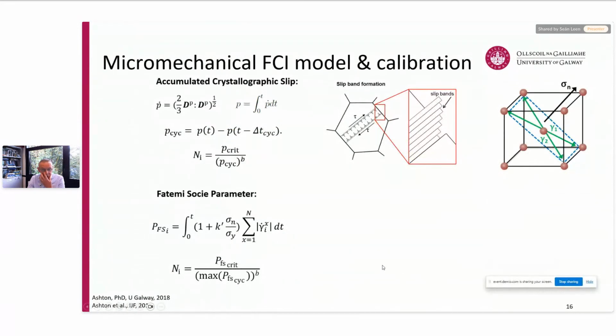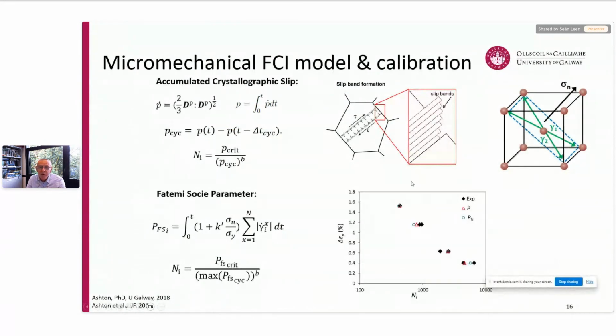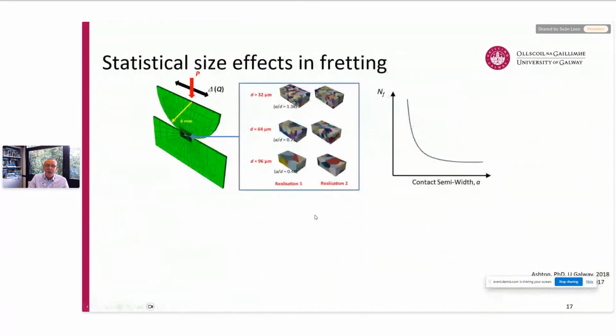And then that allows us, essentially, these are physically based. The intention is to capture the slip band formation idea within the grains. That's the kind of approach. And you can see here a calibration against experimental data, crack initiation data in the bottom right for that type of model. I won't go through the details again, but then we've implemented that to look at statistical size effects in fretting, to look at this contact size effect.